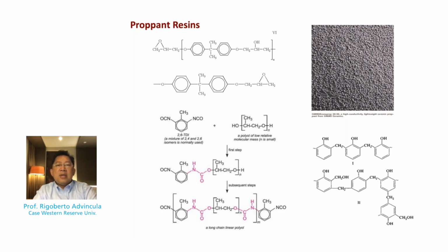Now, that is not the only type of resin coating available. The epoxy coating is also a well-known product. Epoxy comes from the reaction of epichlorohydrin and bisphenol A, but really there are many choices for epoxy or epoxy phenol formaldehyde combinations. Epoxy refers to the group that reacts together with the hardening agent or alcohol to produce a coating. And then other companies have, of course, reported polyurethane. Polyurethane is based on the chemistry of diisocyanate and polyol, the combination of which allows you to get, again, a thermoset resin material based on the number of cross-linkers, or in fact, polyurethane as a thermoplastic can be employed.